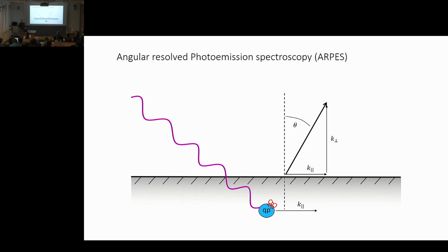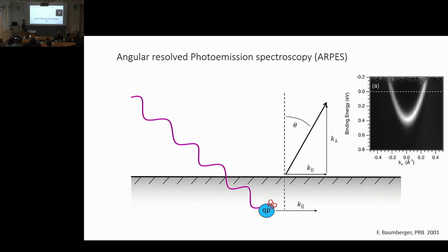I guess most of you know what ARPES is, but to quickly remind you, we use ultraviolet light to excite our quasi-particles in the metal. The energy of those quasi-particles is then high enough to escape the potential. Because of symmetry reasons, more or less, the momentum in plane is conserved. And if we now measure the angle of the ejected electron and the energy, we end up with these nice dispersion bands of the quasi-particles within the metal.